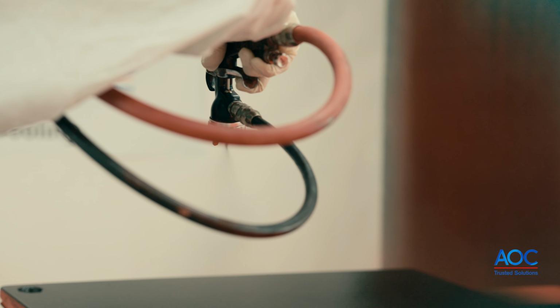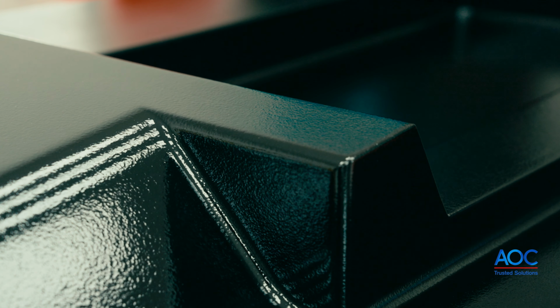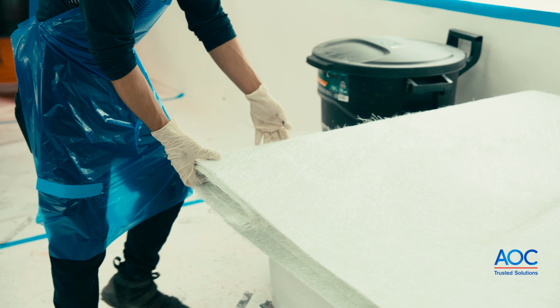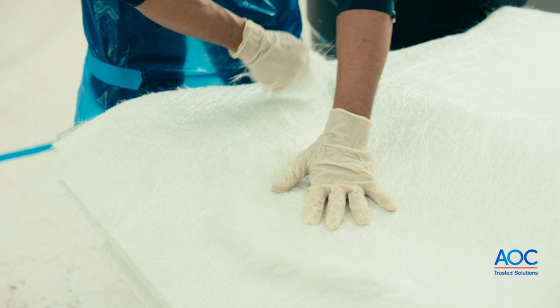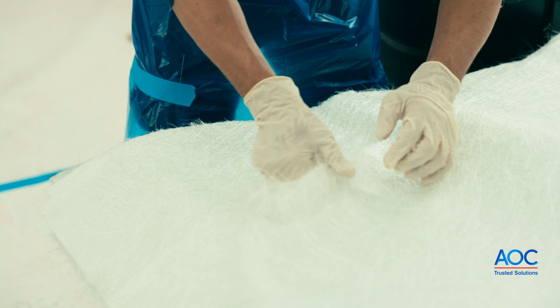Using 2 layers with different colors allows for visually tracking wear on the tool, signaling when rework or polishing may be needed. A skin coat can help detect air bubbles and offers a durable and repairable mold surface, which may extend the life of the tool. When a skin coat is selected, begin by applying 1 to 2 ply of 1.5 ounce chopped strand mat.